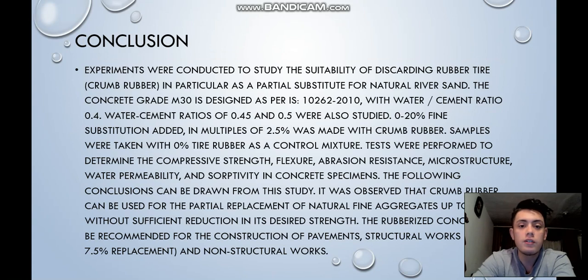Experiments were conducted to study the suitability of discarded rubber, in particular as a substitute for natural river sand. Concrete grades with water cement ratios of 0.4, 0.45 and 0.5 were studied. Percentage substitution was made in multiples with crumb rubber. Samples with 0% tire rubber were taken as a control mixture. Tests were performed to determine the compressive strength, flexural strength, abrasion resistance, microstructure, water permeability, and sorptivity in concrete specimens.